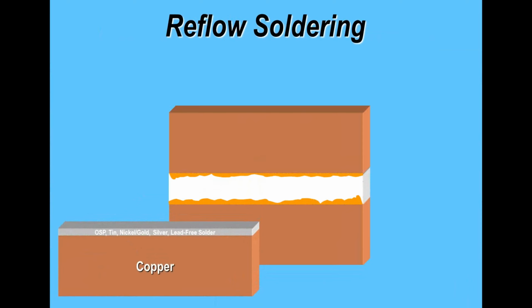So your solder alloy is becoming a liquid, and the tin content of it is forming an intermetallic with the nickel layer. The gold is consumed into the bulk of the solder. With all other finishes, you're soldering to the copper. Really, the nickel gold is the only exception to that rule.